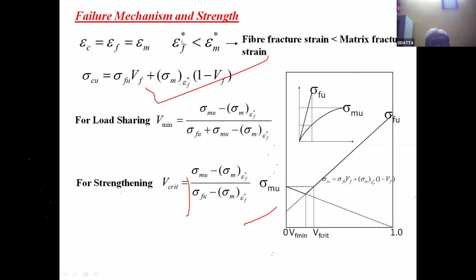And failure mechanism and strength, if we have a look into this, when the load is applied in the longitudinal direction, then composite strain, fiber strain and matrix strain are all the same. But since the stiffness of the fiber is very high, the failure stress of the fiber will be reached first, and then the composite ultimate strength is when the fiber has reached its failure strength. So sigma_fu V_f plus sigma_m at epsilon_f star, when the failure takes place, epsilon_f star is the failure strain, into 1 minus V_f. 1 minus V_f is nothing but V_m.